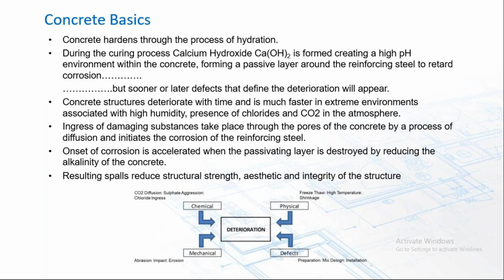So concrete hardens through the process of hydration, and during the curing process, calcium hydroxide is formed, creating a very high pH condition within the concrete. It forms a passive layer around the reinforcing steel that retards corrosion. But sooner or later, defects that define deterioration will start to appear. Concrete structures deteriorate with time, and much faster in extreme environments associated with high humidity, presence of chlorides, CO2 in the atmosphere, and wet and dry cycling.